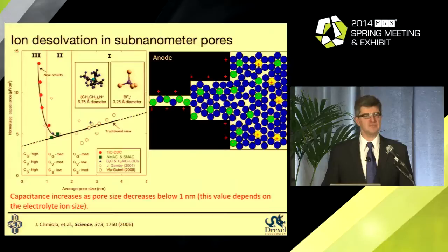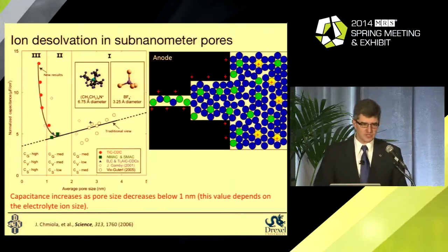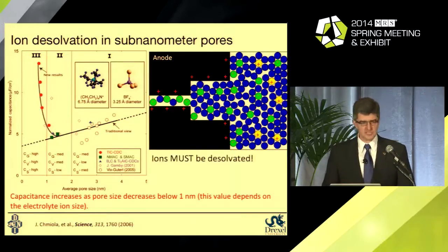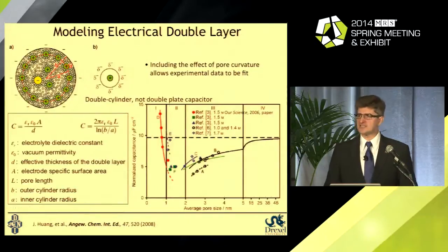So a natural and very simple explanation was that ions go into pore without solvation shell, at least partially naked, losing some of the ions in solvation shell. As a result, we can pack more ions since this solvation shell is lost. The distance between the charges becomes smaller, capacitance becomes larger. And this seemingly simple result led to really a dramatic change in the entire development of capacitive energy storage devices, attracting the attention of researchers, moving scientists into this field, and understanding there is a lot of design that can be done.